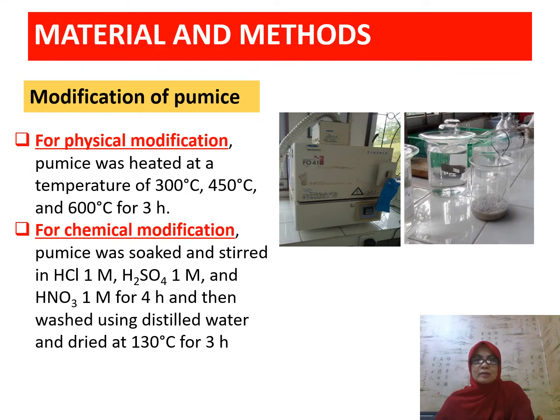And then we conducted the modification of pumice. For physical modification, pumice was heated at temperatures of 300 degrees Celsius, 450 degrees Celsius, and 600 degrees Celsius for 3 hours by using this furnace. For chemical modification, pumice was soaked and stirred in 3 kinds of acid solution. They are hydrochloric acid, sulfuric acid, and nitric acid at concentration of 1 molar for 4 hours, and then washed using distilled water and dried at 130 degrees Celsius for 3 hours.